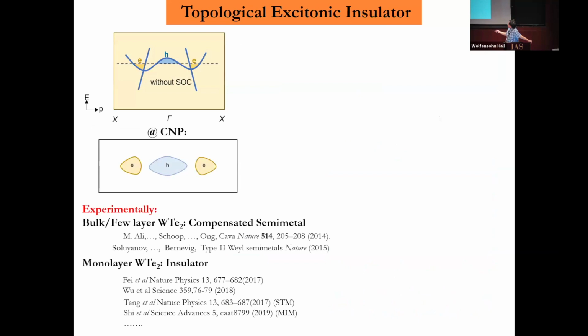If you look at the Fermi surface at charge neutrality - meaning you just exfoliate it and look at how many electrons and holes you have - it looks like this for electrons. So without the gap, in a single-particle picture, before you see the insulating state, you have electron pockets on the two sides of the hole pocket in this rectangle.